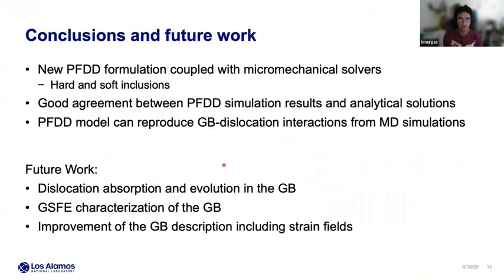To wrap up and summarize the presentation: we developed this new formulation, we have good agreement with the analytical solutions, and we can reproduce the grain boundary dislocation interactions from MD. Some of the future work is to simulate the absorption and the evolution in the grain boundary. Sometimes, as I mentioned, the dislocation can get compressed at the interface between the bulk and the grain boundary, and then the leading partial dislocation can glide along the grain boundary. We are working on that, and we already have all the tools to do it, so that's probably going to be finished soon.